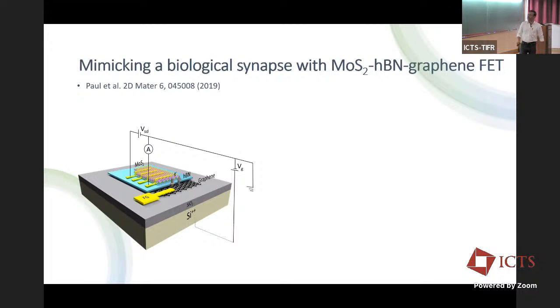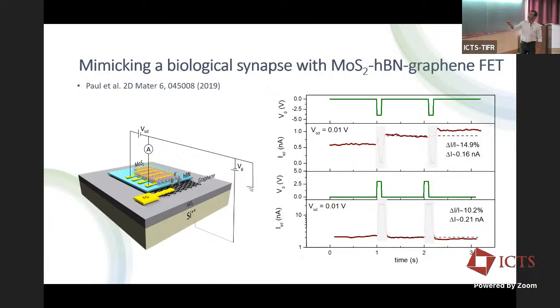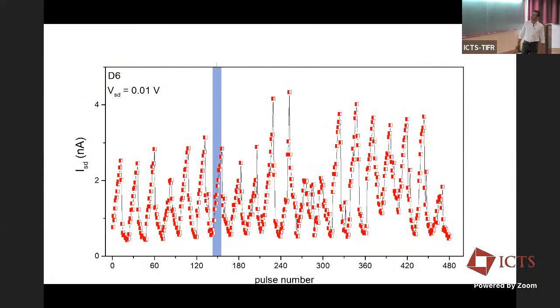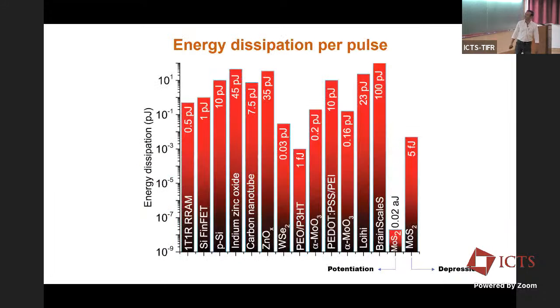that decreases the resistivity. So you can see the change in potential pulses. This is the pulse applied to the bottom gate here. You can see the change in the current. If I put a negative pulse, it essentially increases the current, because more and more charge comes out, and that change makes this channel conducting. And if I put opposite voltage pulses, exactly the opposite path of charge makes the channel more and more resistive. So it's like a memory. And we have made beautiful potentiation and depression activities for many, many cycles, and showed that this can lead to a very interesting neuromorphic device. What is interesting is that energy dissipation per pulse is actually even smaller than what the human brain takes in a single memory action, which was quite interesting, because you can operate such electronic devices at a very small conductance level.